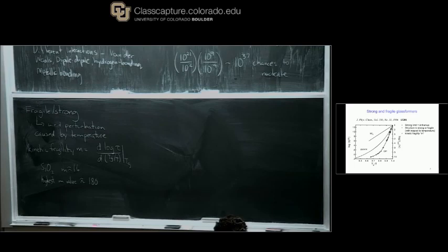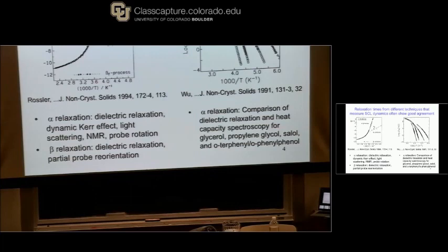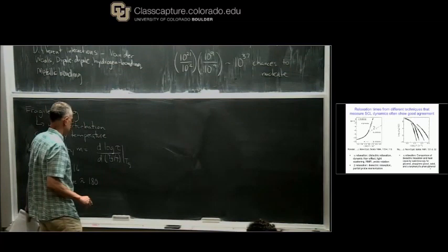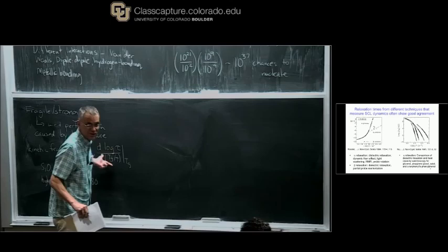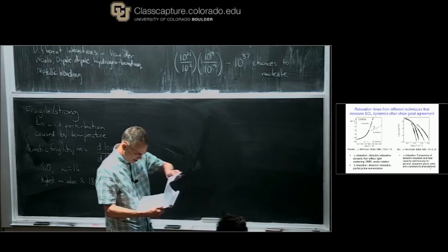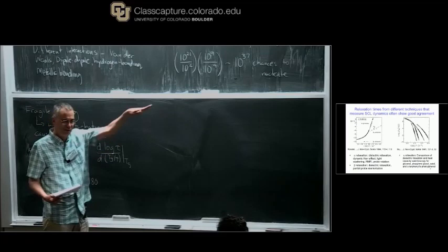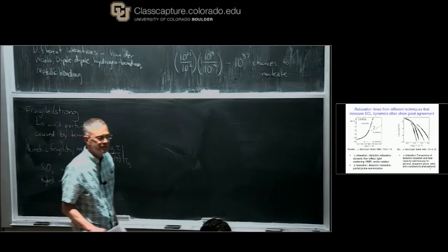So there was a great question about what's an alpha relaxation time. It's time to get into more detail about exactly what these times are that we're measuring. When defining M, that's the derivative when you're approaching in the equilibrium state. This comes down to the definition of TG, which I'm going to come back to later. Just trust me and say that you need to evaluate this in equilibrium, because for example there's a kink along the glass line — you don't want to evaluate it along the glass line out of equilibrium.